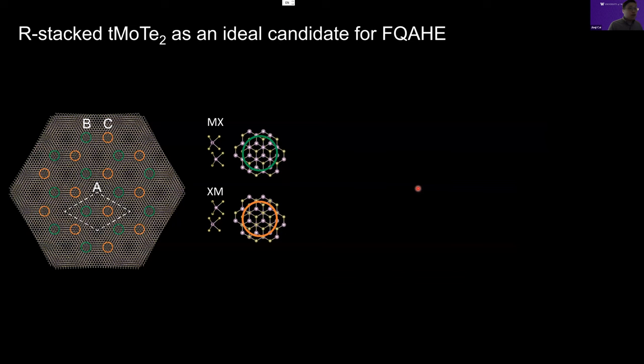So today I will introduce our recent discovery of the fractional quantum anomalous Hall effect in R-stack twisted MoTe2. If you stack two transition metal dichalcogenide layers, molybdenum ditelluride, together and twist with respect to each other with a small twist angle, you can form this large scale Moiré, and note the B and C sites. If you dope electron or hole into the system, an electron will sit on this B site or C site. The stacking property of the B and C sites is different. For the B site, the top layer is metal and the bottom layer is chalcogen, so the electron will localize on the upper layer. On the other hand, in the C site of the Moiré superlattice, electron or hole will localize on the bottom layer.